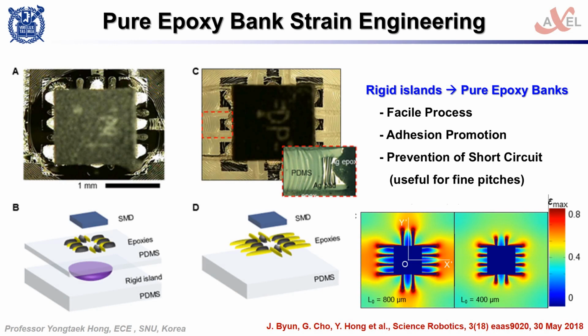The same effects can be obtained by using a pure epoxy bank printing process. When ICs have fine pitch contact pads, there is a high chance for short circuit formation between pads when silver epoxy is used for bonding.